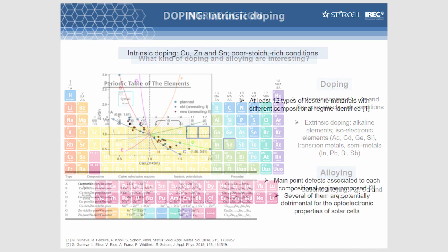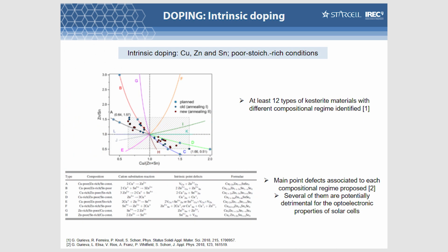Then starting with doping of kesterite, this was already presented by Susan, and the main thing is that we don't have just one kesterite. We have at least 12 different types of kesterite. And this is just changing the kind of intrinsic doping, the composition of kesterite. And each of these kesterites has particular different point defects, and several of them are really detrimental. So first of all, to understand this is extremely relevant. All the work presented by Susan is really the most important starting point, because we will understand at which kind of intrinsic doping we have to work, and then try to improve this intrinsic doping.